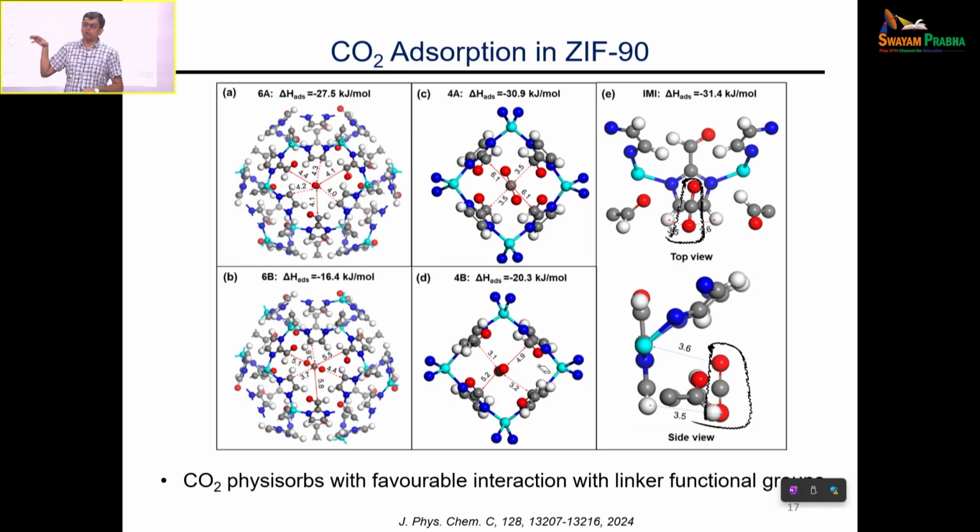So, the way most adsorption happens in many of these materials, if they are perfect, is by physisorption, okay. If there are defects, and I will not be talking about defects for now, defects could be metal sites where the linker is not coordinated. So, these metals are coordinated with 4 linkers in this particular case. There is no place for interaction with that particular metal site. So, the linker is 4 coordinated here. In that case, there is absolutely no way chemisorption is possible. So, the interaction here is primarily physisorption, but even within physisorption, okay, what you see here is